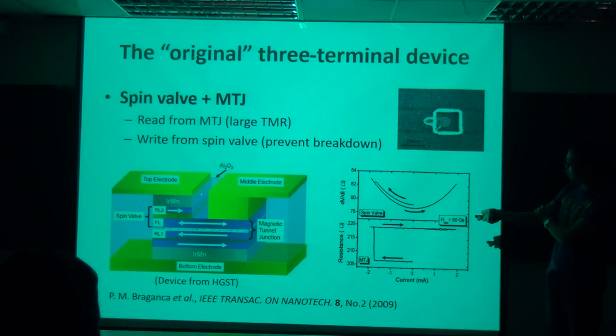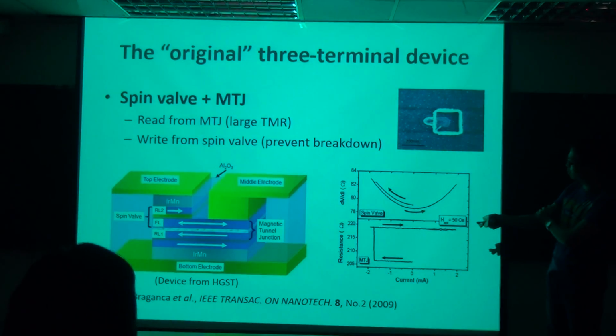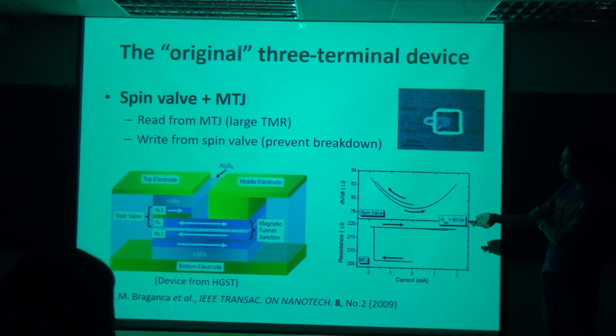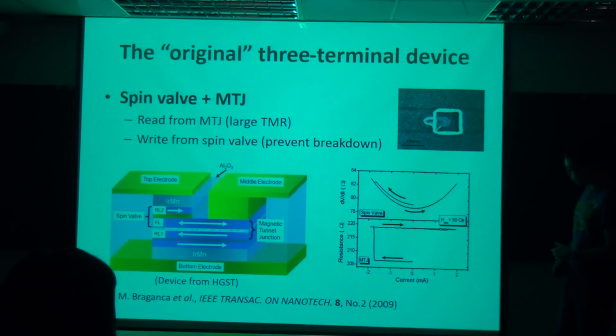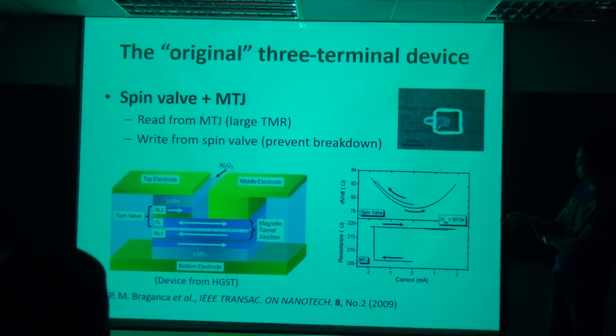mill through several layers and stop right at the ferromagnetic layer here, using e-beam alignment, lithography, and also some etching techniques, RIE or ion milling, and put down these two electrodes almost perfectly on top of this part and this part, and they can't overlap, because right after putting down these two electrodes, we have to put down this aluminum oxide insulator in order to make sure that the current will flow through this part.